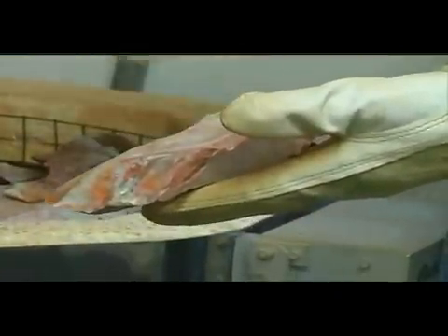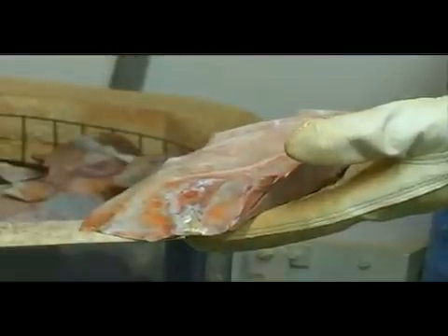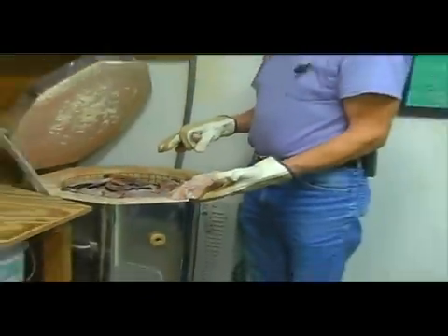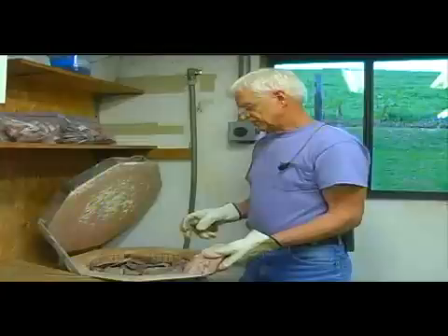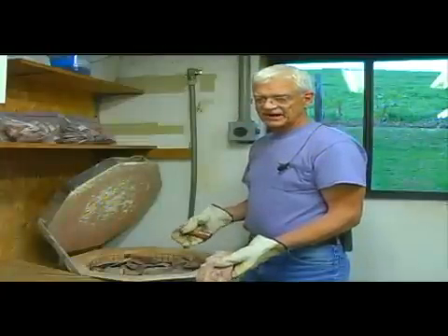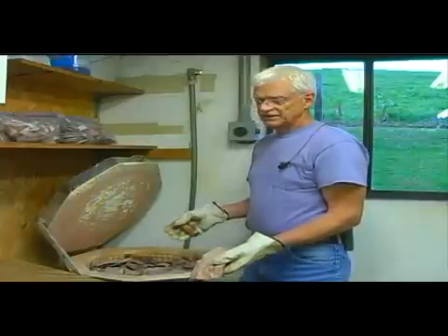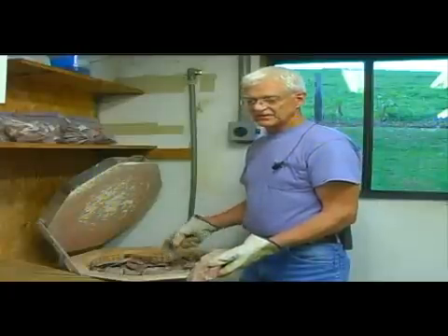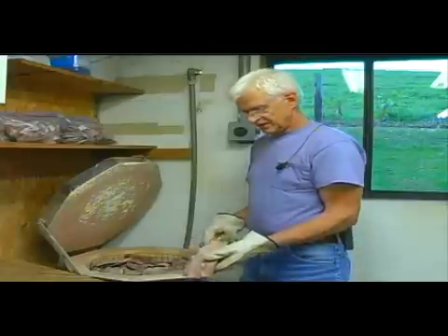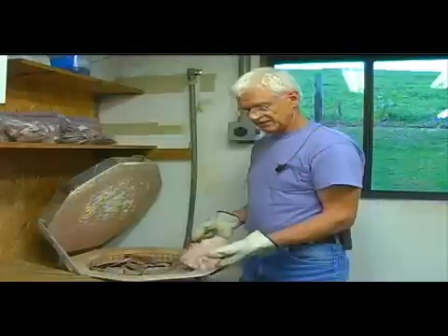When I start heating, I put the flint in and take it up to about 250 degrees. I run it up within an hour to that point, because that does not destroy the flint at that low a temperature. I hold it for 5 to 10 hours to dry it better. Then I run it up 25 degrees an hour until it comes to about 500 — this particular flint is 535 degrees. It takes about 30 to 35 hours to do that whole process.